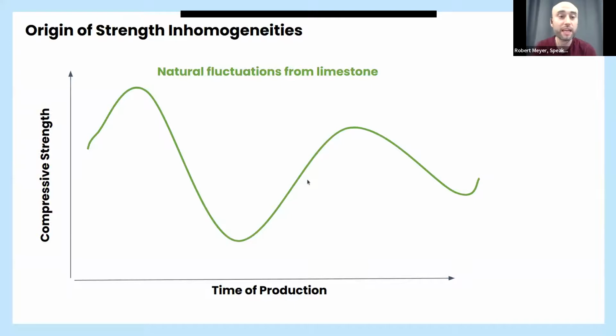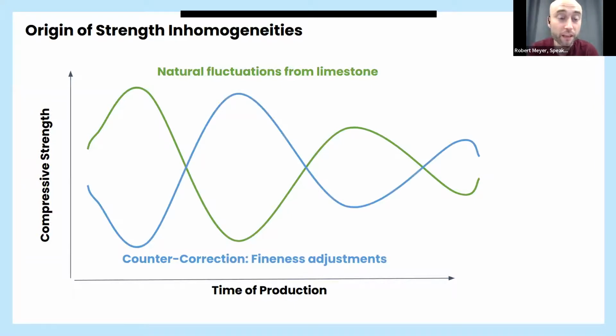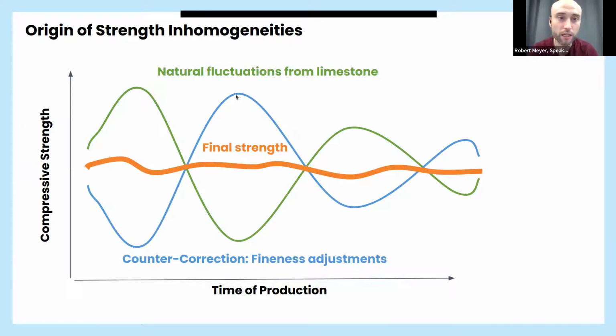So the idea now is that we counterbalance these fluctuations with another property that has a strong influence on the strength of the material, and that is the fineness. Because the more finely I grind my cement, the more surface area it has to interact with the water and to actually get stronger. So if I have some limestone that yields high strength cement, I can counterbalance this by grinding much more coarsely and vice versa. If I have something that doesn't get very strong, then I grind more finely, and due to this counterbalancing, the resulting material will be very reliable and have a homogeneous strength over weeks or a month of production.